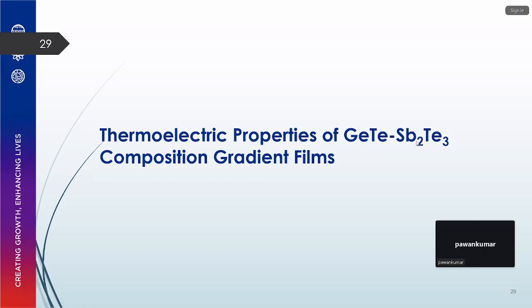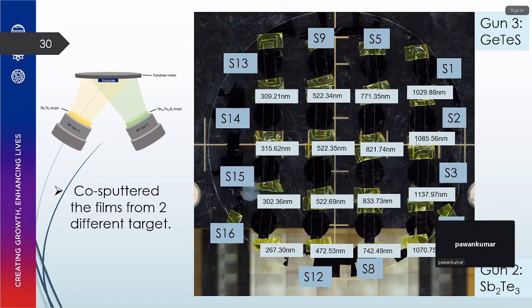So quickly I'll present. I've been working on this material for the last 1.5 years. We have a co-sputtered film of germanium telluride and antimony telluride from the Rob Simpson group. They do sputtering, so they're growing a film for us on a 4-inch quartz wafer. They have 2 targets, antimony telluride and germanium telluride, and they co-sputtered on the quartz surface for us. This wafer has about 16 samples with different ratios of germanium telluride and antimony telluride.